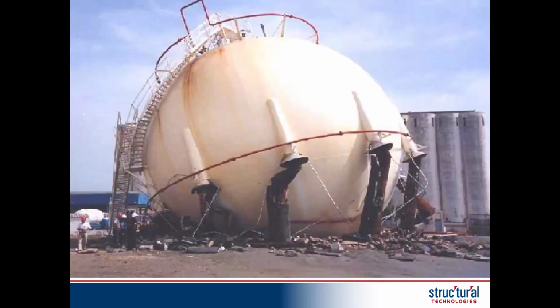This particular photo is actually one that's off the internet. It was a very spectacular failure. Unfortunately, one individual was killed, another in very serious condition. They were inspectors. Believe it or not, this was during a testing exercise where they filled it. They hydro-tested it up to 80% of its capacity, and that hydro-test is actually heavier than its service loads. And what happened, even though the fireproofing looked great on the outside and it was regularly painted and everything, what they didn't understand was the corroding pipe columns underneath, and that essentially just failed and sat itself down. So very spectacular failure, but very tragic.